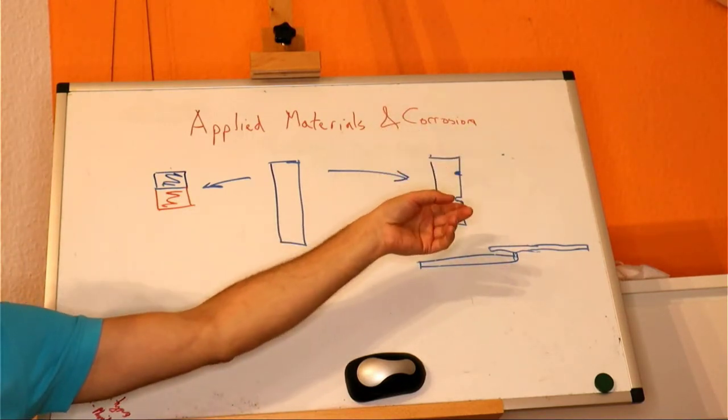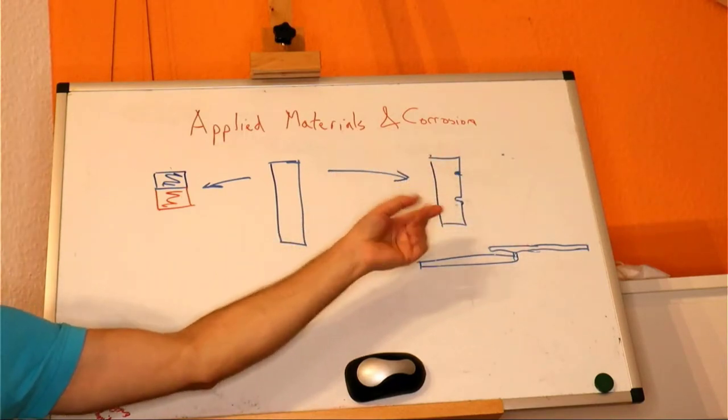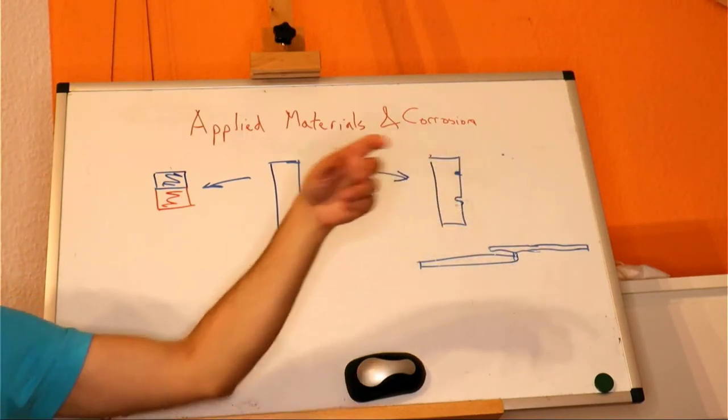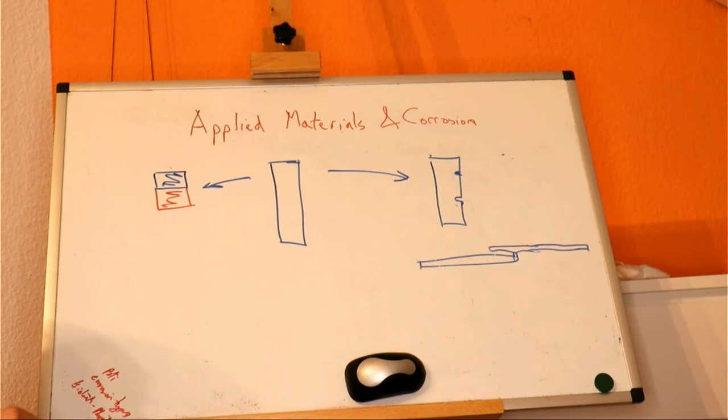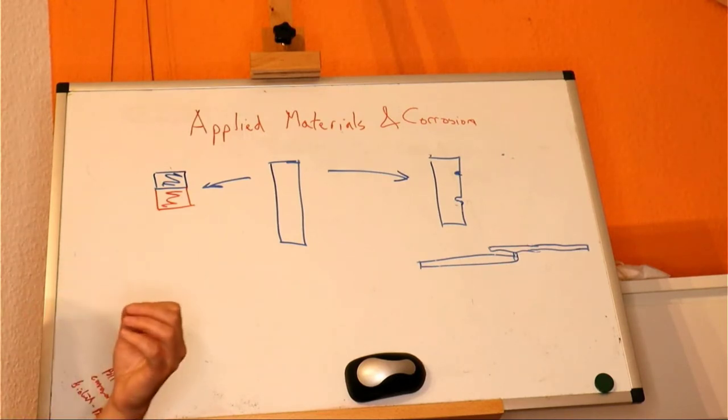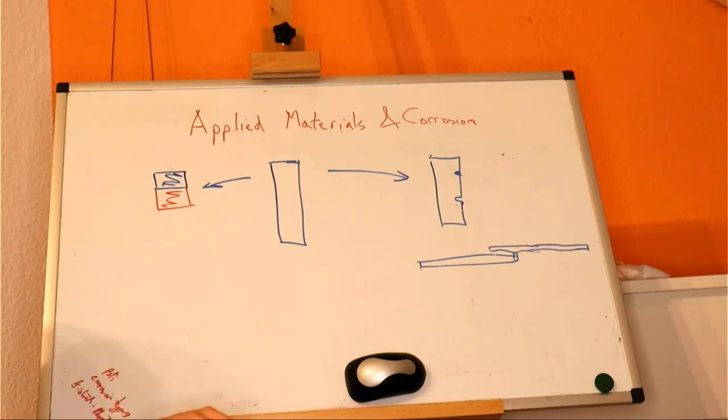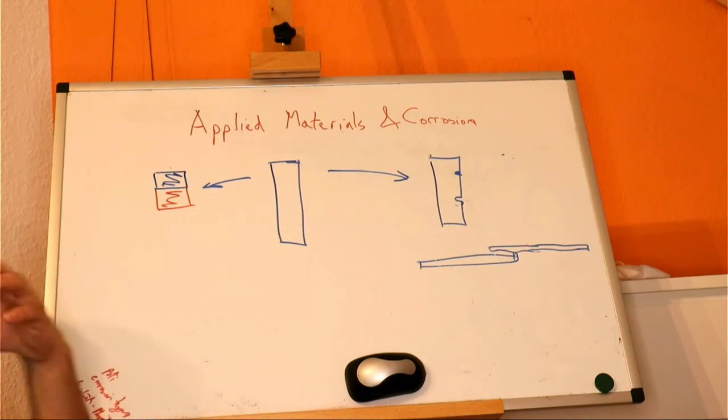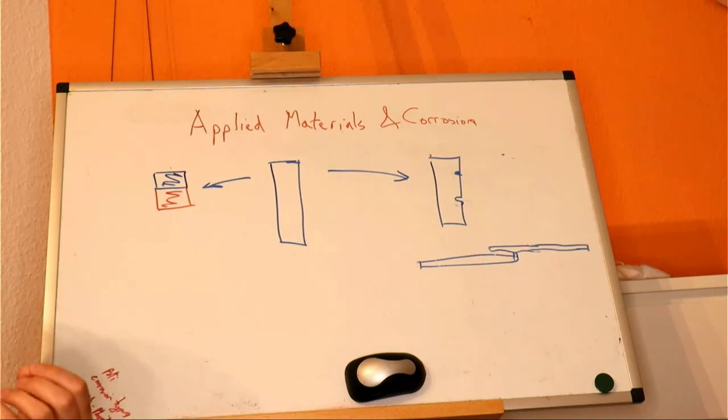the reduction of oxygen will happen on the outside. The oxidation of zinc happens at the bottom of the pit, and that's obviously bad, because then we will tend to make a hole all the way through our zinc, and instead of corroding at a rate of micrometers per year, it's all focused on a few points and we'll tend to get through it very quickly indeed. So if we change the mode of corrosion, we are likely to generate a problem.